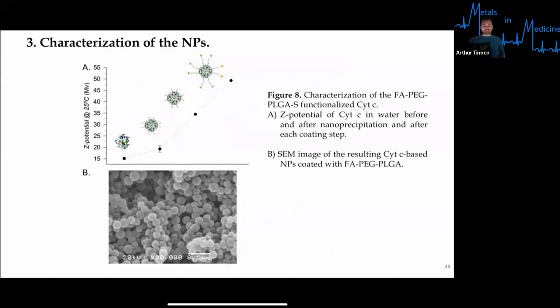All right, so a few of the characterizations. Here, what we're looking at is the spherical structure of these nanoparticles, with the full nanoparticles and the coating. You use SEM here to capture that image, but also look at, along the way, how you transform the cytochrome C particle with the coatings, what happens to the zeta potential. You can see that with every modification, there is a change in the zeta potential. Going from just the cytochrome C nanoparticle, we're at a zeta potential of about 15, all the way up to when you have the full conjugated functionalized cytochrome C, up to about a value of 50. So there is a significant change in the zeta potential of this actual structure.